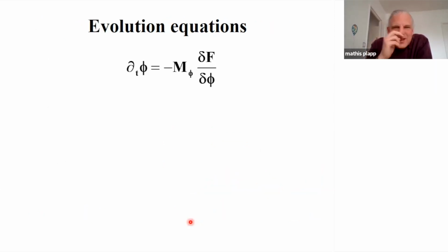So in order to get the evolution equation, I can just use two things. So the order parameter adjusts itself to the local thermodynamic conditions. So it will also always tend to the state that locally minimizes the free energy. So this symbol here is the variational derivative of the free energy with respect to the order parameter. And this is nothing but a relaxation equation: it always goes downhill to find its local minimum, with a kinetic coefficient that is called the phase field mobility.